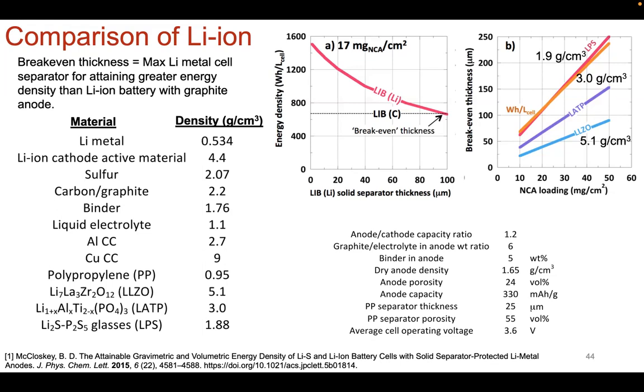So if you increase the solid separator thickness, where will you break even to compete with state-of-the-art lithium-ion batteries with a graphite anode? That's what's done here. As you increase the thickness, you can see here, you can get out to 100 micrometer thickness of the separator to then achieve parity with a lithium-ion battery with a graphite anode that doesn't need an additional separator for lithium metal protection.